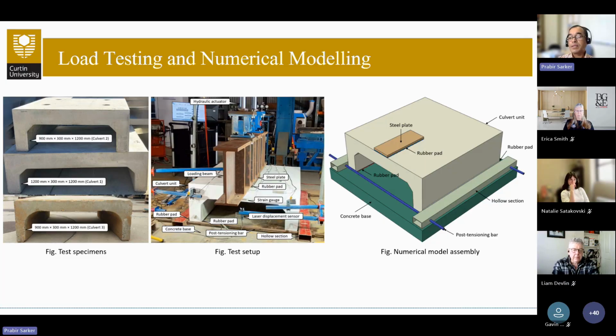So this deterioration, like estimated section loss by deterioration and also estimated reinforcement loss by corrosion, can be included in the numerical analysis to predict the load capacity of existing structures. This needs validation of the numerical method by some test results. So we collected some new culverts, and we were fortunate to get two old culverts from main road sites, and we tested those culverts in the lab.